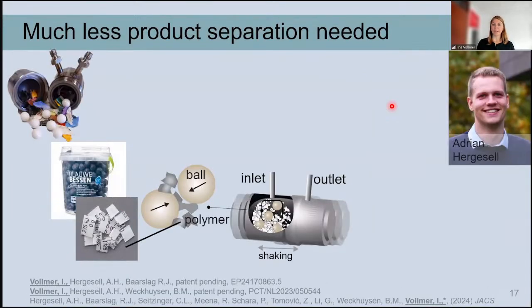And so the way we apply the force is in a ball mill. And this is a small vessel that shakes back and forth. And you can see this vessel here where you can actually see inside. And so when the grinding spheres inside it collide with some polymer in between, then it will experience the force necessary to break these carbon-carbon bonds. So you can also see an image of the opened up vessel here with the grinding spheres made of zirconia and then the solid polymer. And this is what we actually put inside.